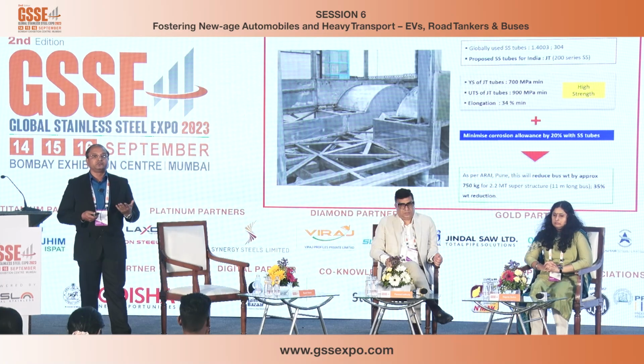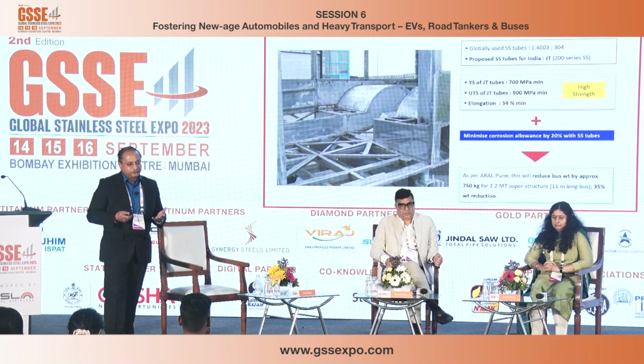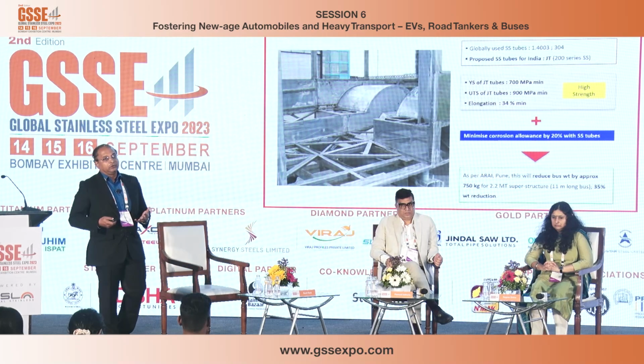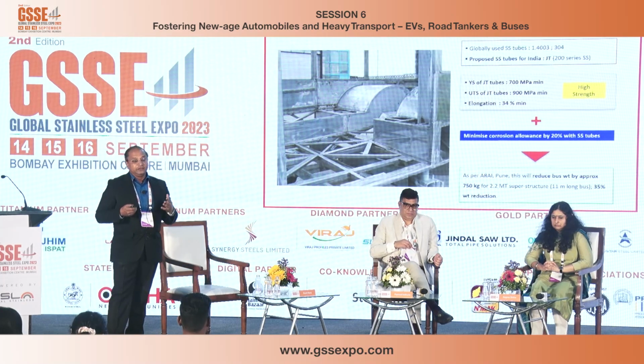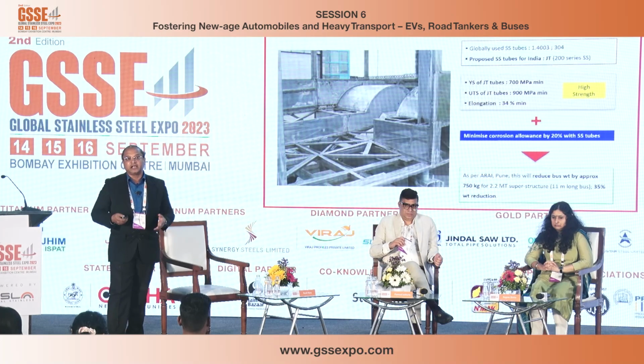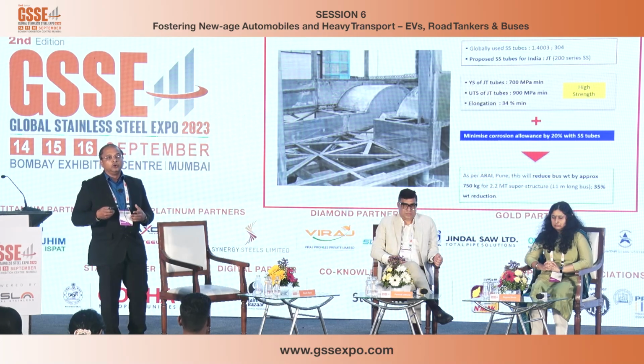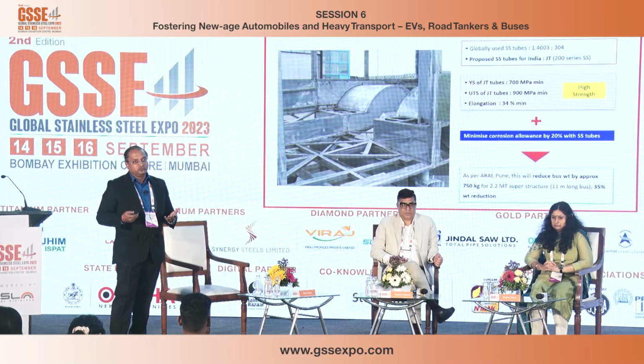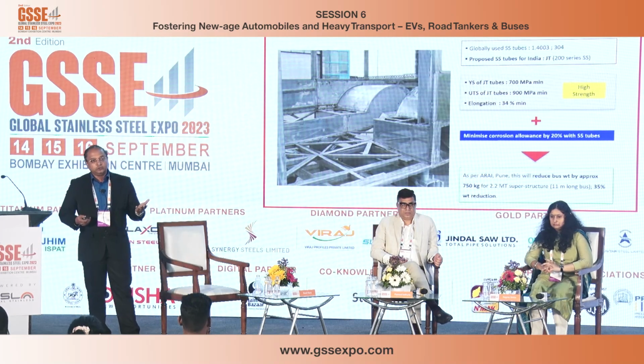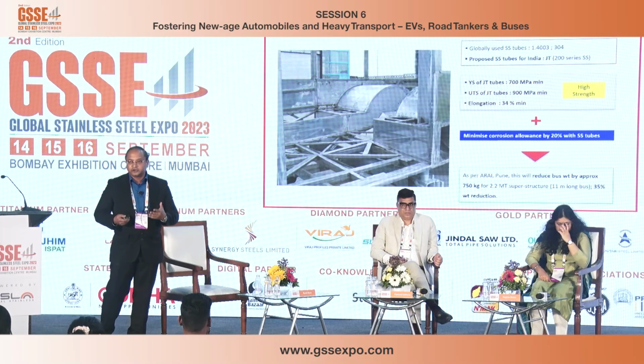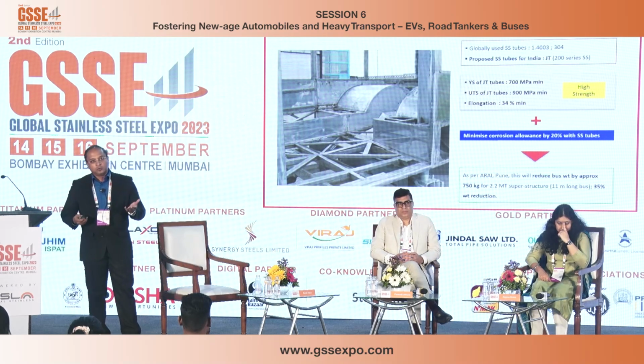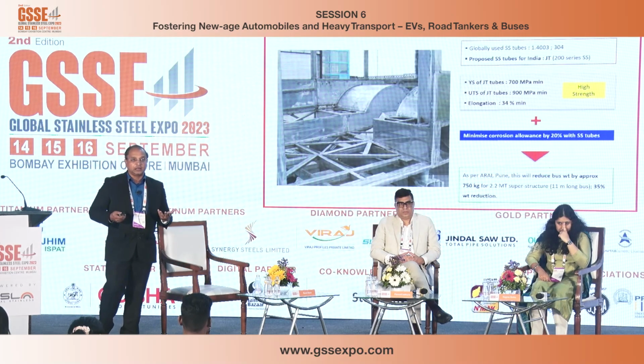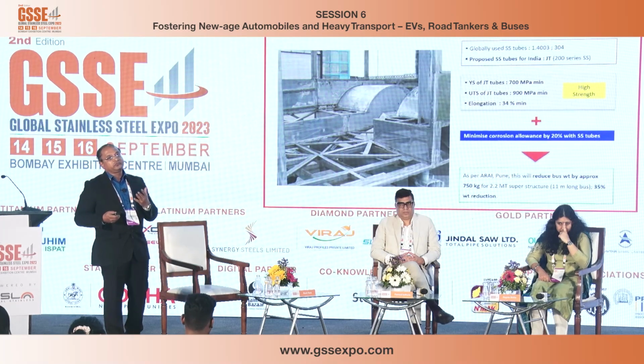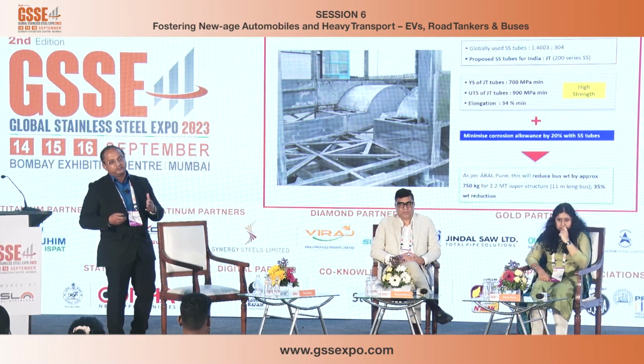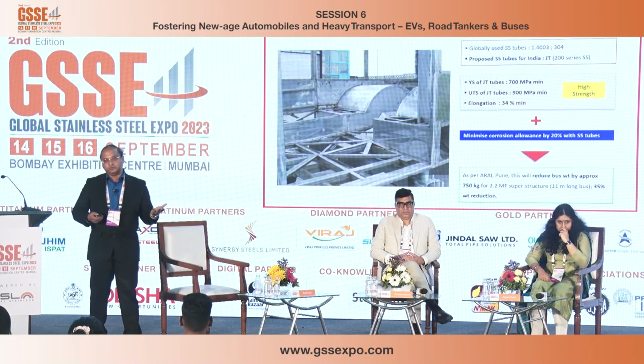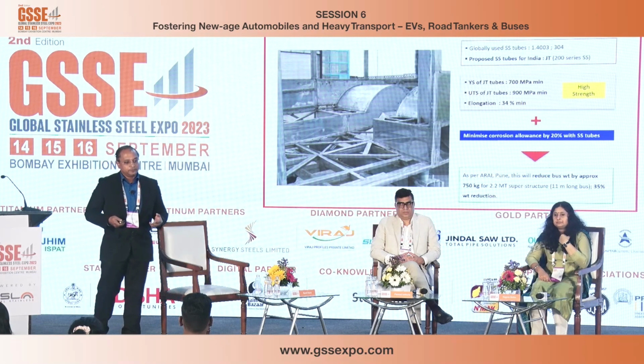One is in terms of the yield strength. As you can see, the yield strength of this particular grade is 700 in the tube form. It's 700 megapascal minimum. Whereas if you look at the GI tubes which are being used today, they are either YST 240, that means the YS is 240 megapascal minimum, or YST 280, that is 280 megapascal minimum. So it's almost 3 times, the strength levels of this particular grade is 3 times that of the GI tubes.